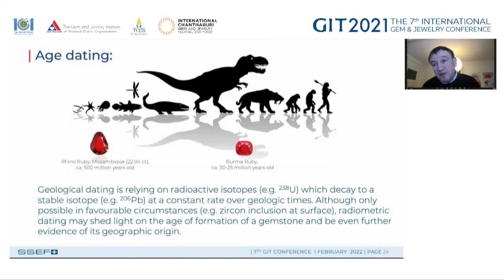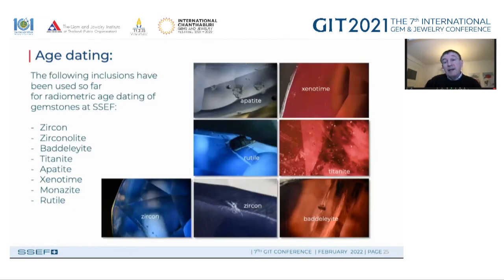And to end up, finally, we can talk about the age of a stone. And we can talk about age dating, which is relying on radioactive isotope, for example, uranium, which then transforms or decays to a stable lead isotope. This is the common, normally used way to go through. And this is a method where we finally can say something about the age of formation of the stone, but definitely also it helps us in some cases to say something about the origin of a stone. At SSEF, we use plenty of different inclusions like apatite, rutile, zircon, xenotime to do age dating. Important is that this inclusion is touching the surface, is at the surface. Only by this we have access with our GemTOF instrument.